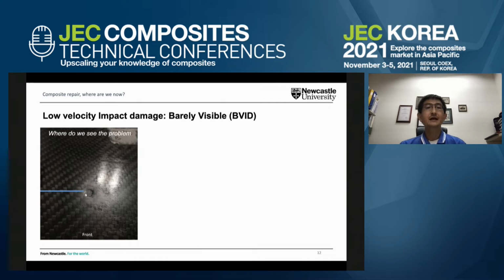the damage, like for instance, damage arising from low velocity impact, as simple as a tool drop or even a knock. And what we find is that these lead to barely visible damage. As the name suggests, it's barely visible to the naked eye in most cases. And you can see this at close up, showing the indentation due to the impact.